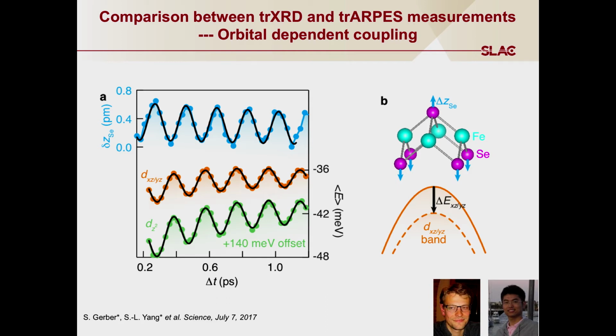That's the critical motion of this particular layer atom, and you can see the signal to noise. The full scale is less than 1 picometer, okay? In a diffraction that gives you that level of sensitivity, the two lower curves are the energy level of electrons moving, both at 5.33 terahertz, and you know they were related to the motion of that. From that, you can say, okay, I know how much my lattice moved, less than a picometer, and how much my energy level moved. From that, you can verify you are in a linear response regime, and then you can measure the deformation potential.